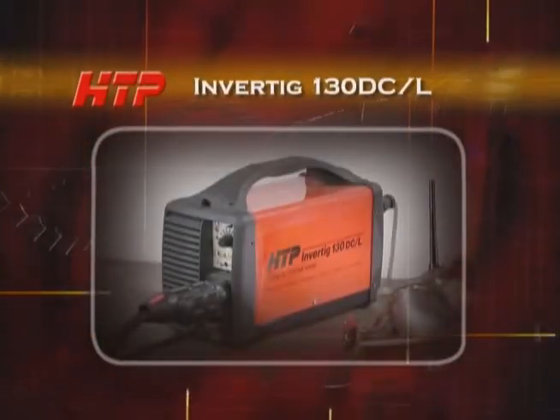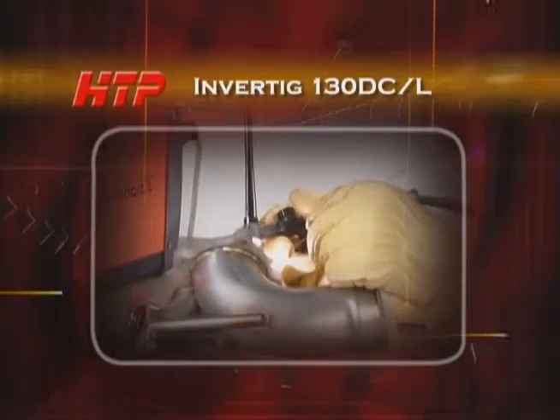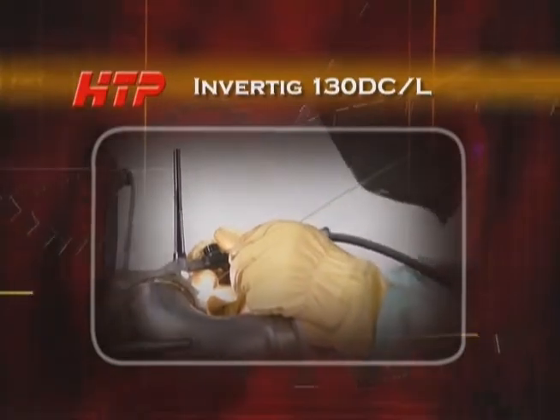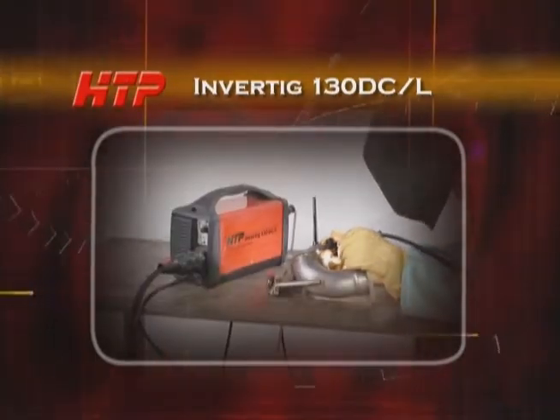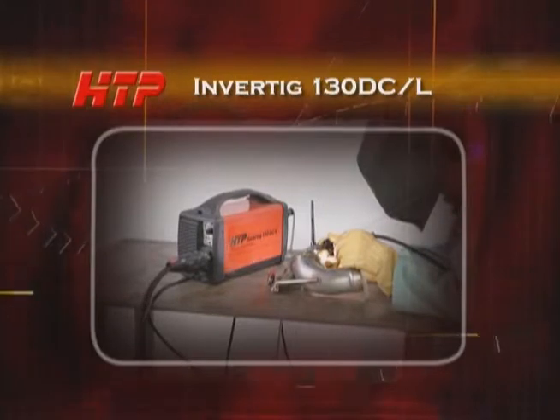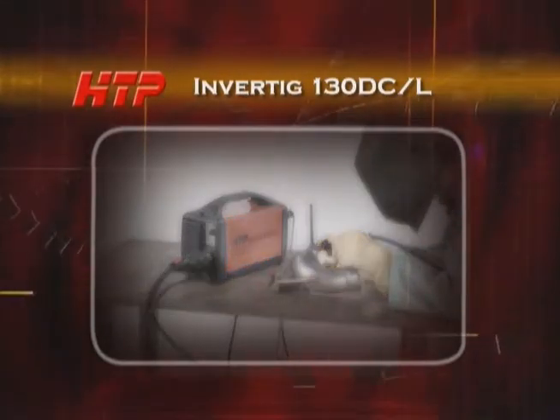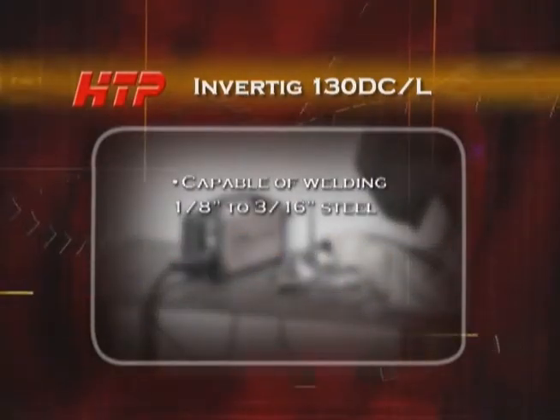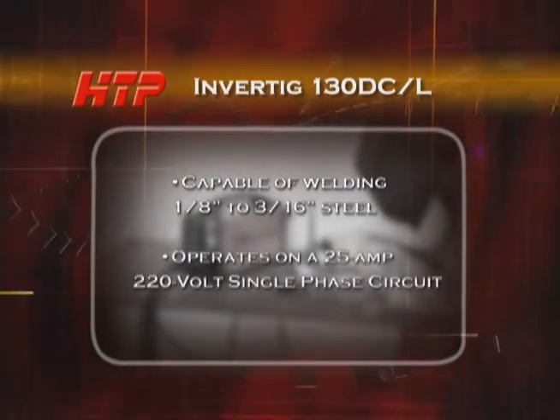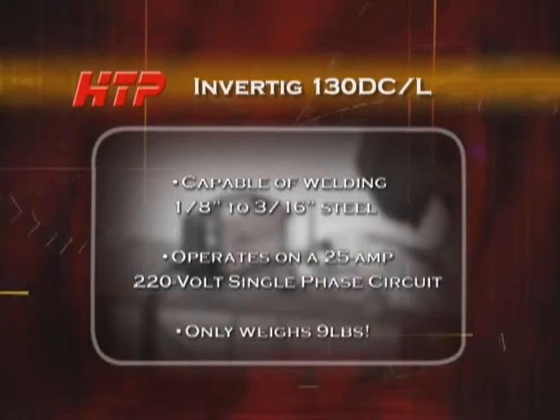HTP currently has 5 different TIG welders in the lineup. The InverTIG 130 DCL is a DC TIG stick welder, so it can weld steel, stainless steel, but not aluminum. The 130 DCL is a 130 amp machine, so it is capable of welding 1/8 to 3/16 inch steel depending on the application. The unit operates on a 25 amp 220 volt single phase circuit and only weighs 9 pounds.